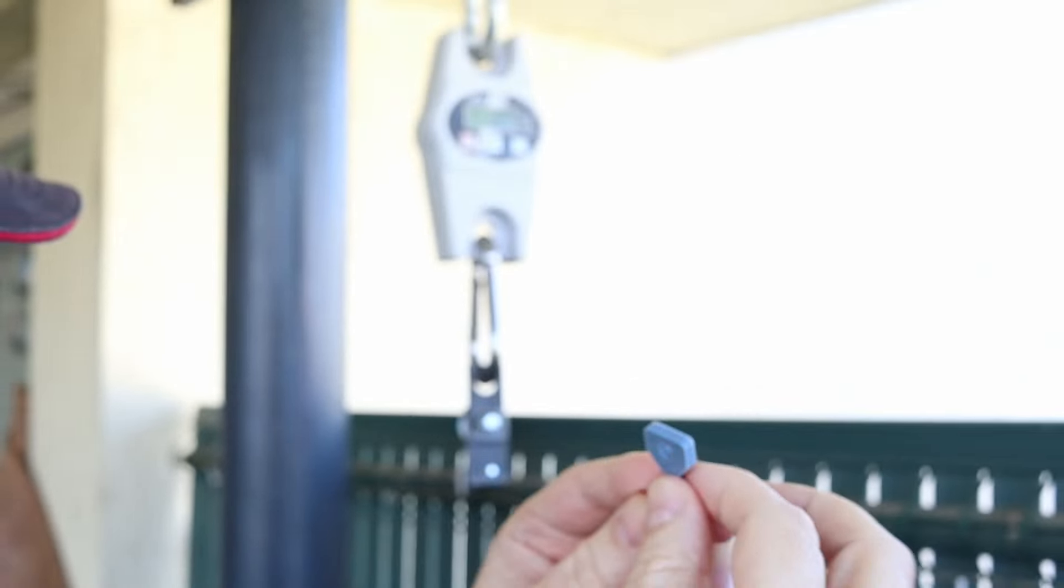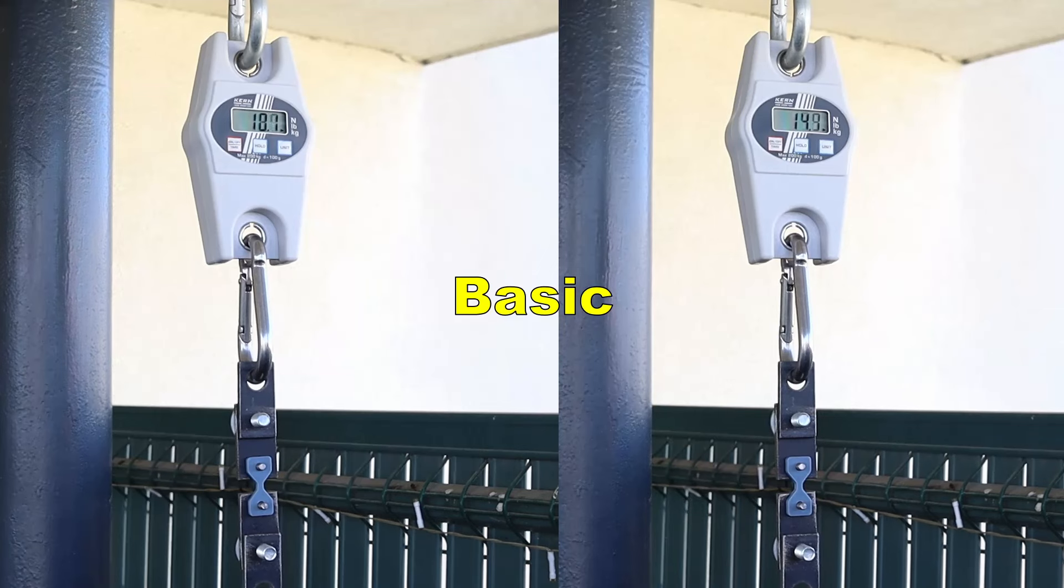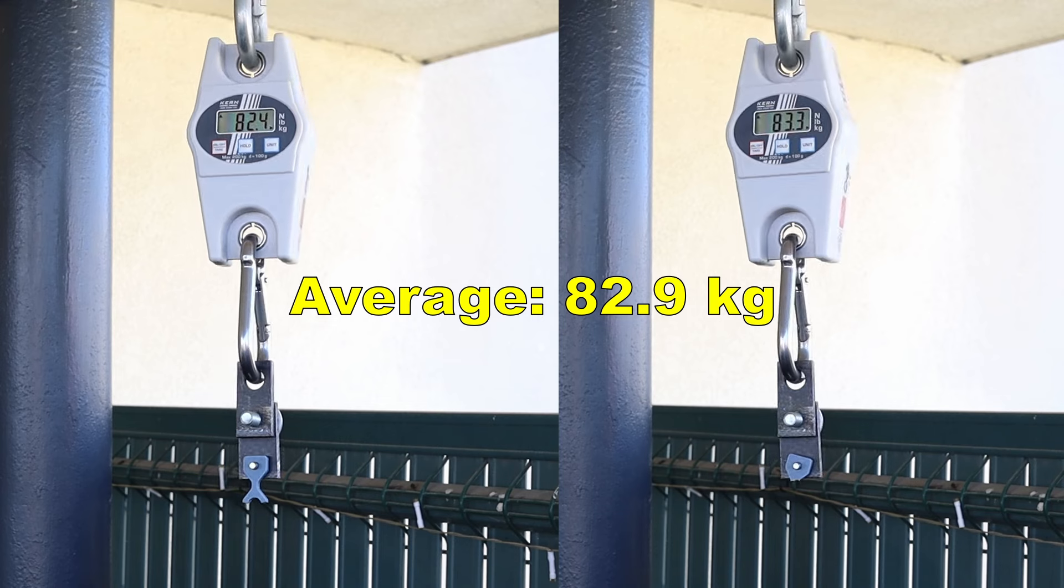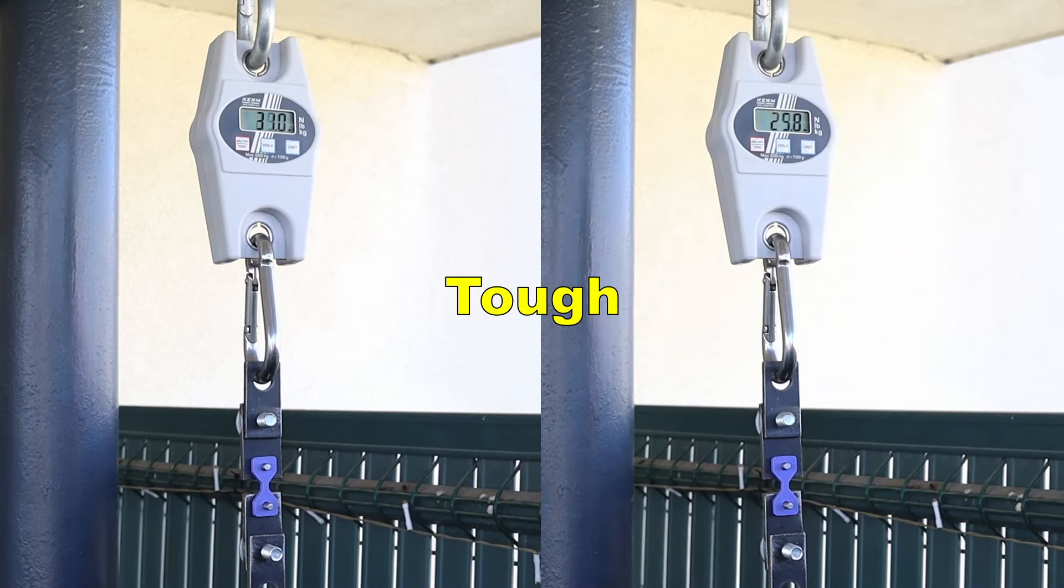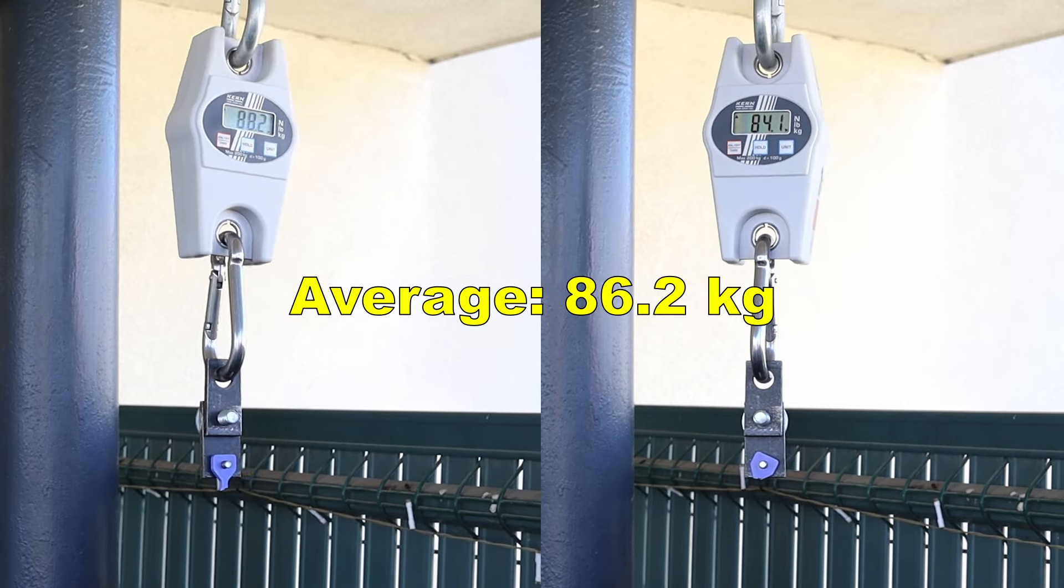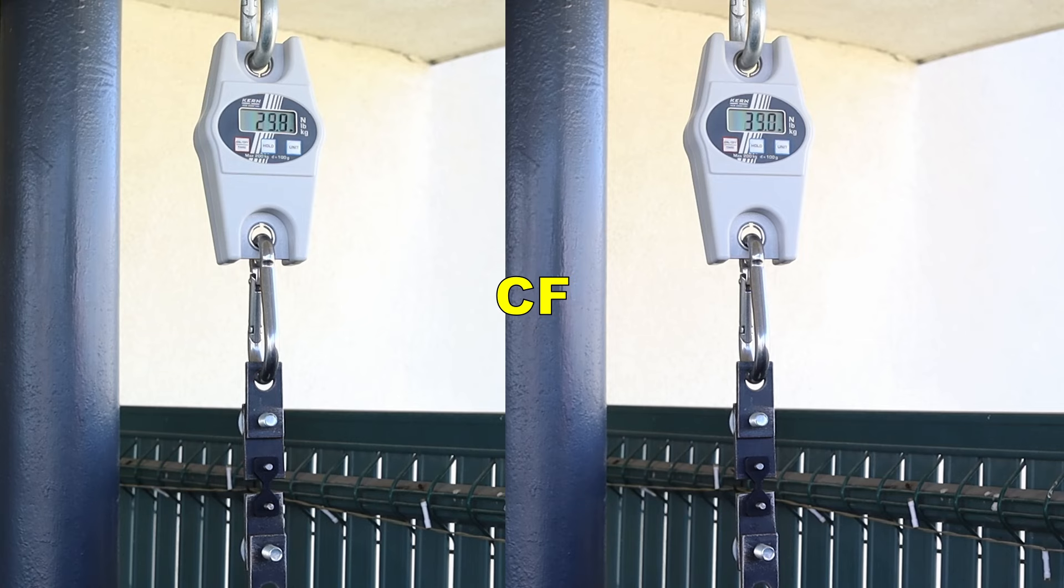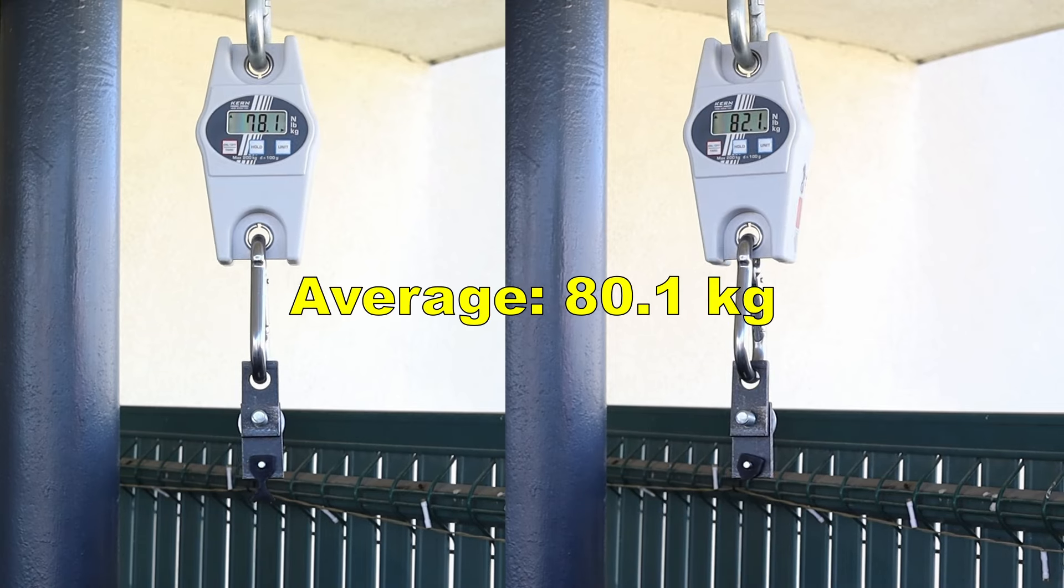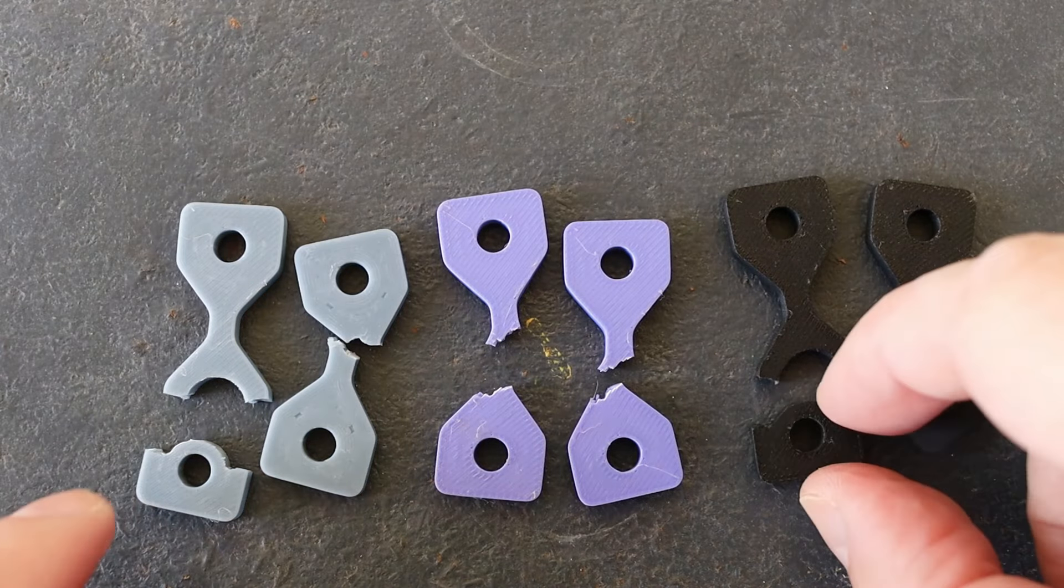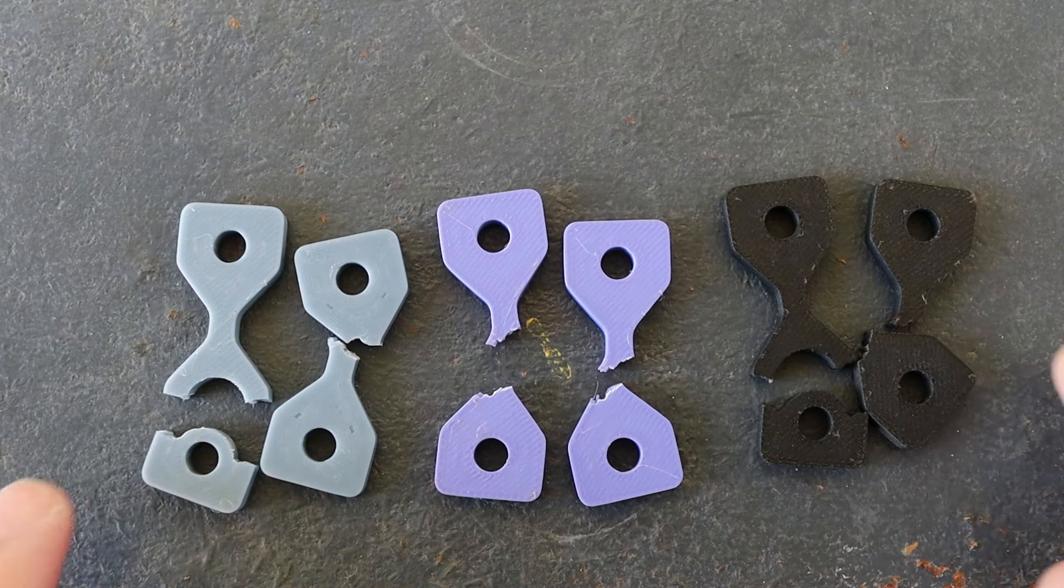The tensile or pulling test with horizontally printed test objects. I am starting with PLA Basic: 82.9 kg average. And then the TUF version: 86.2 kg. And this is the carbon fiber version. A little bit weaker but similar results. The break load is very similar but it is interesting to see new types of break. I didn't see this kind of break earlier.